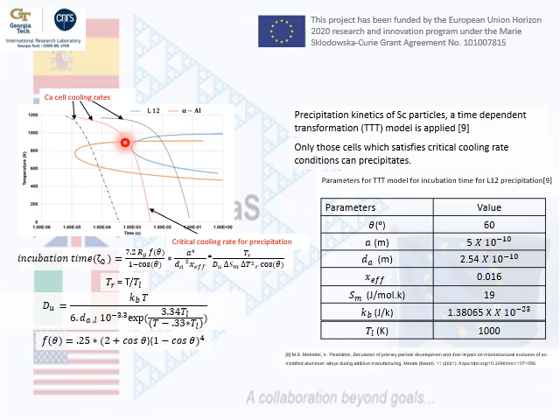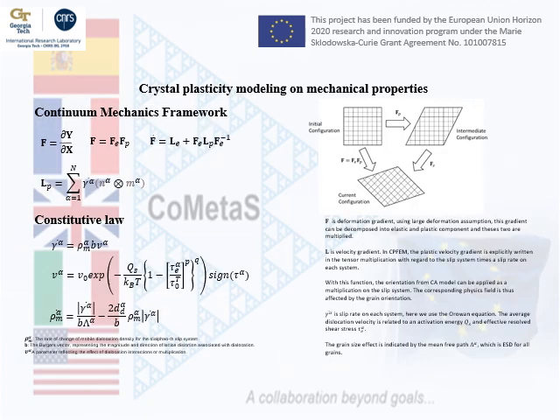And we would like to also implement this into the models. To this end, we utilize a temperature-time transformation diagram based on an Avrami scheme to consider the probability of nucleating a particle of scandium and aluminum, right? So for example, here we follow the different cooling rates, right? And then if we intersect or pass across a zone where we observe the formation of a specific phase, then the probability of nucleation of a particle is going to increase, right? And once we have considered the nucleation of this particle, we can also consider an increased probability of a crystal nucleating there. Okay, and this is going to result in a very specific microstructure, as we're going to see in the next slide.